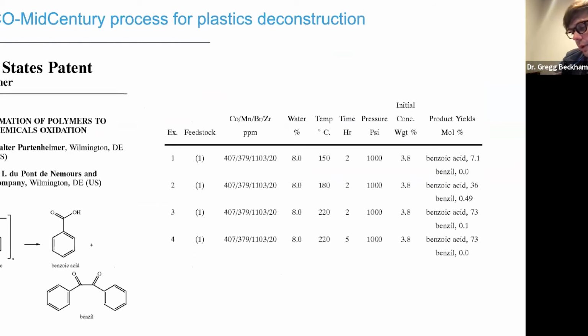And towards the end of his career, Walter Partenheimer started trying this mid-century Amoco process on a lot of different substrates. He tried this with cellulose, with cotton, with lignin, as well as with single plastics. And there's this beautiful patent that he wrote and was published in the early 2000s. And what he showed, and we got really excited about this, is you could take the mid-century Amoco process, which uses cobalt, manganese, bromine, sometimes with a little bit of zirconium, in the presence of water, in acetic acid mostly though, at fairly mild temperatures and fairly short residence times. And you could take, for example, polystyrene and make, you can see 73% yield of benzoic acid.